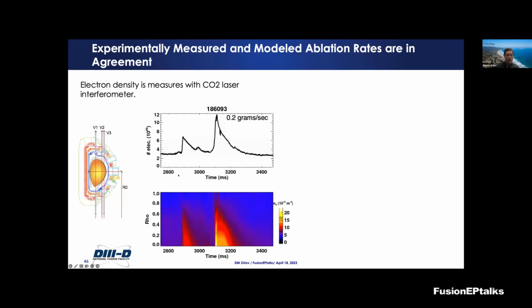What we could also do was try to estimate how much material was ablating from those pellets as they went into the plasma. On DIII-D, we have the electron density measured very fast by the CO2 laser interferometer. Of course, we have a lot of diagnostics like Thomson scattering, which is probably the better one, but it doesn't have good temporal resolution for the time that the pellet goes into the plasma and ablates.